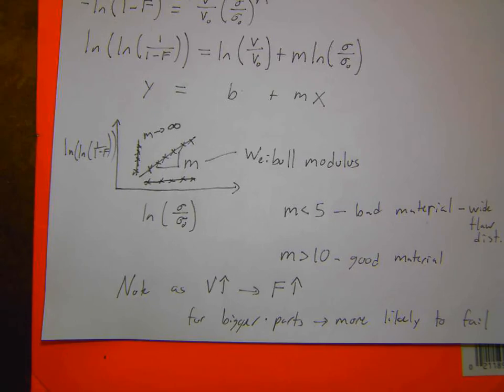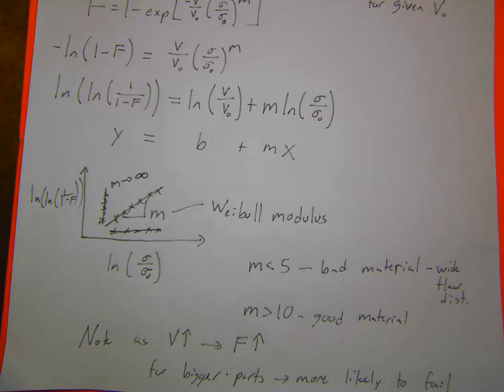We're working with, or just starting something with PACCAR right now, the truck company, for making a thermal swing coating in the inside of a piston housing. So for that, you want a material that's going to have ultra low thermal conductivity and also not have any thermal mass. So when you have cool air coming in, you want that cool air to stay cool. And if your chamber heats up, then it heats up the cold air and ruins your thermodynamic efficiency. And so you want a material that doesn't have the heat transport through it, which is a ceramic, but you also don't want something that's going to carry any residual heat. So you want a porous ceramic, a lightweight ceramic that's mostly air.